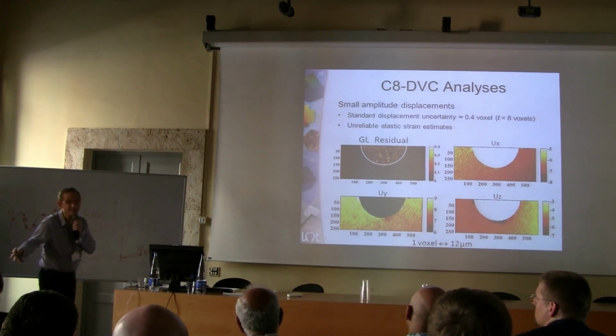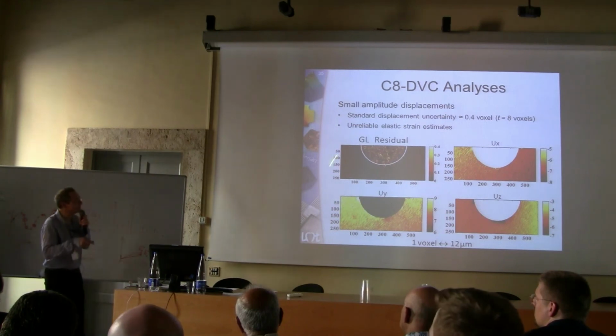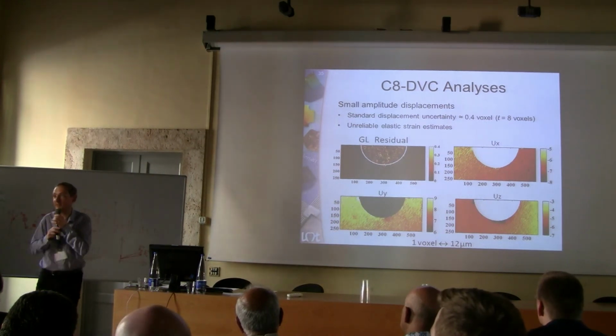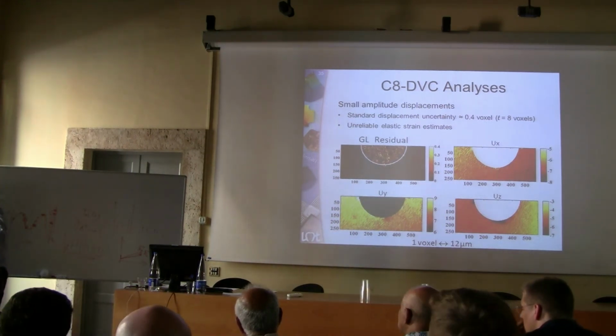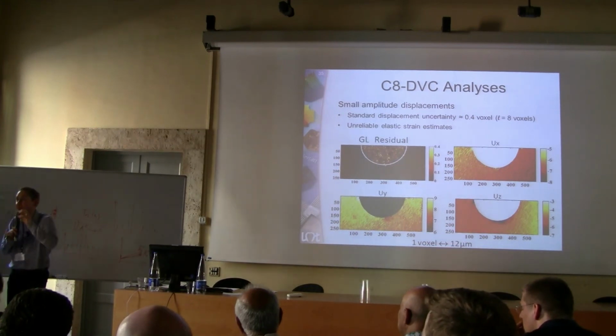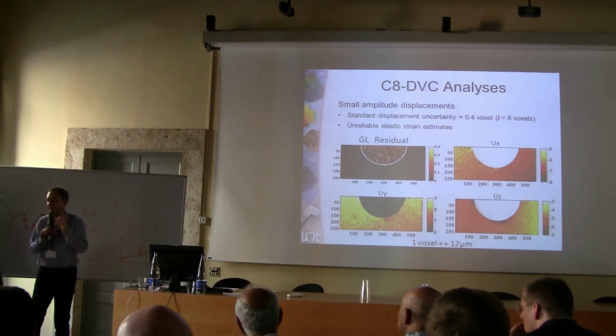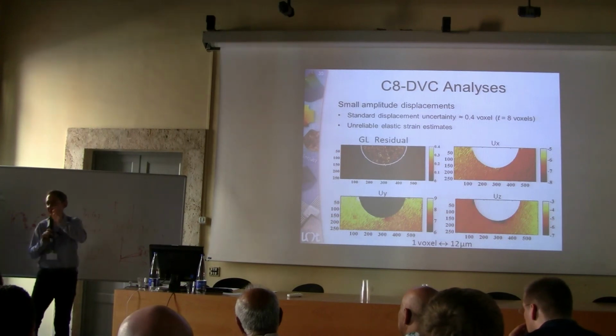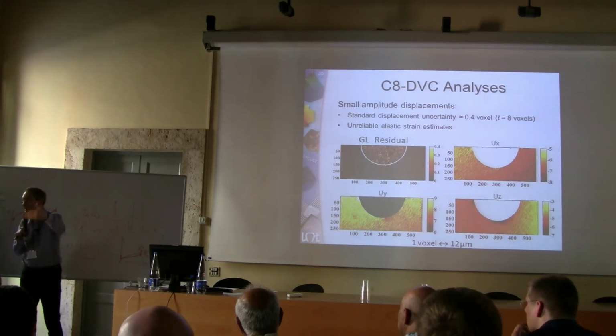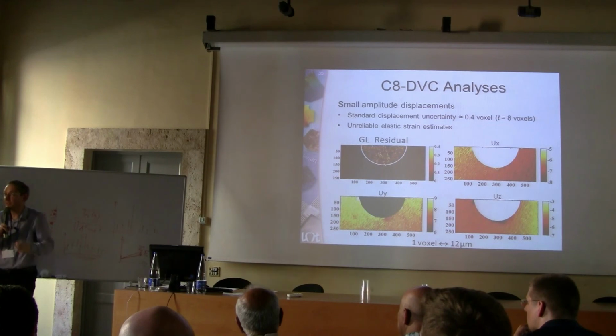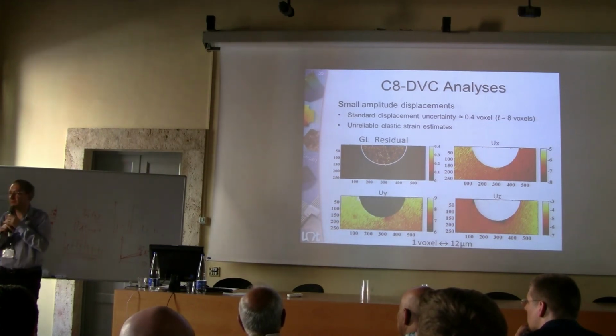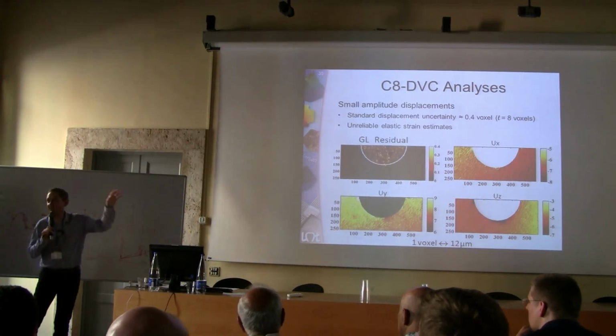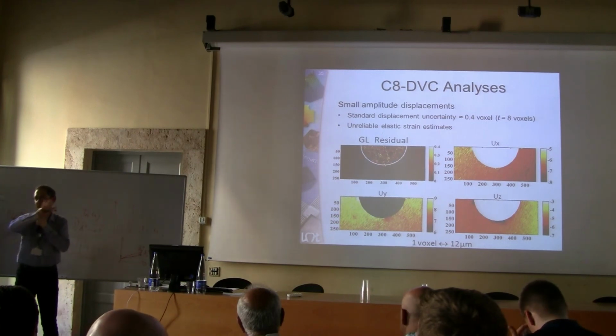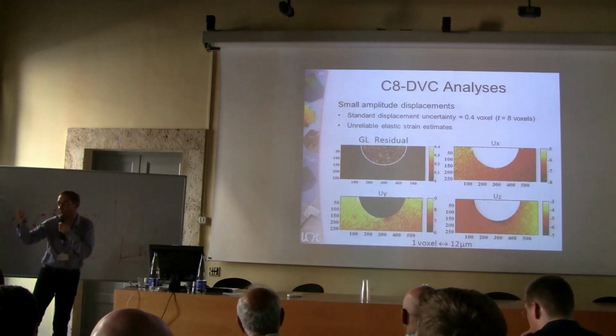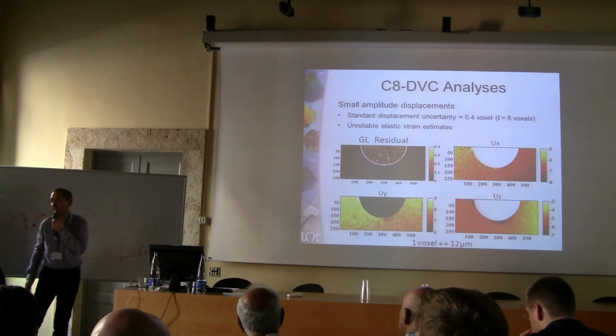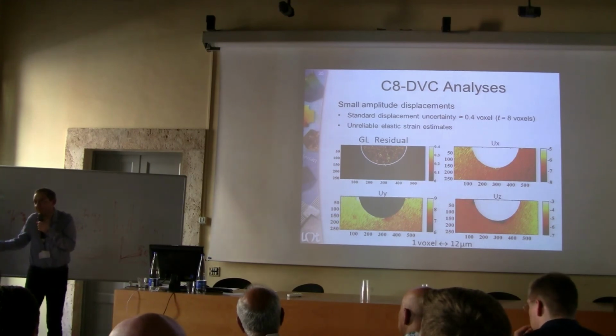We would work with some wood or alloys - did you verify the approach with this material? Well, not yet, but I may argue that plaster is an interesting material because it's essentially elastic, as you mentioned, but you also have this crushing mechanism. So you had to understand the transition between elasticity and a nonlinear, even softening material, but thanks to the fact that indentation basically stabilizes everything, you can at least start constructing part of the constitutive model.